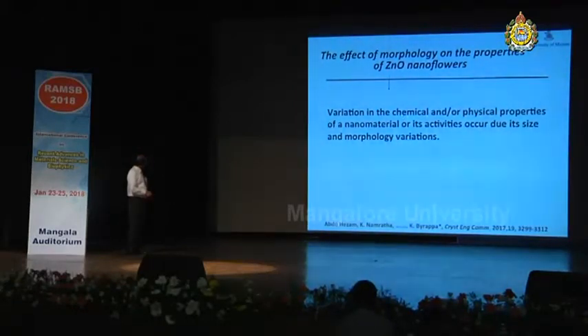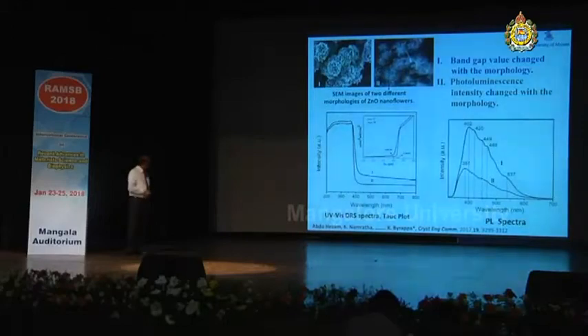So, the variation in the chemical and physical properties of a nanomaterial or its activities occurs due to its size and morphology variation. And this I am going to show from the characterization studies we have carried out. These are the two typical samples we have selected, zinc oxide nanoflowers with two different morphologies, sample 1 and sample 2. We have calculated the band gap, and the values change with the morphology between these two, and also the photoluminescence intensity changes with the morphology. This is the UV-visible DRS diffuse reflectance spectra, and the top plot showing the band gap, and this is the PL spectra of these two samples.